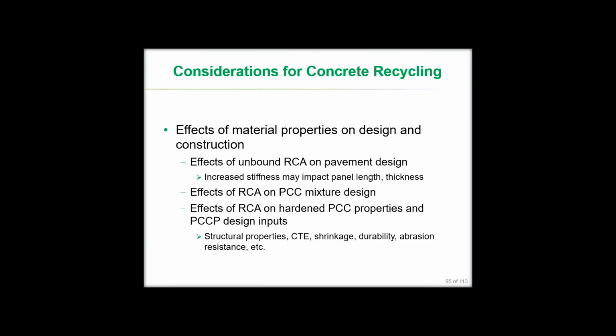There are some direct considerations for concrete recycling on design and construction. The effects of the unbound recycled concrete on pavement design. It does have a secondary hydration process in which you will have what is initially an unbound material, but over a number of years it will become more stiff, and that additional stiffness may mean that you would have higher curling and warping stresses, so that might impact your panel length requirements. If you want to reduce those stresses, you would reduce the panel length. Might also impact the thickness, either to offset higher curling and warping stresses or to be reduced because you have a greater stiffness pavement there, greater stiffness foundation. Becomes almost a stabilized base.